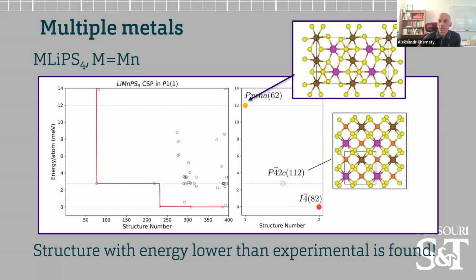So it is possible that kinetics comes into play. It is possible that as we elevate the temperature, the situation is different. Though in this particular case, we're pretty confident that it's not the case because we also calculated the free energy, including the phonon subsystem, and we still find that the structure we found is the lower energy. But it is also possible that whichever method is used to synthesize this structure does not allow it to go to the true ground state. So that's something which we have to run with our experimental collaborators and see if that makes any sense.